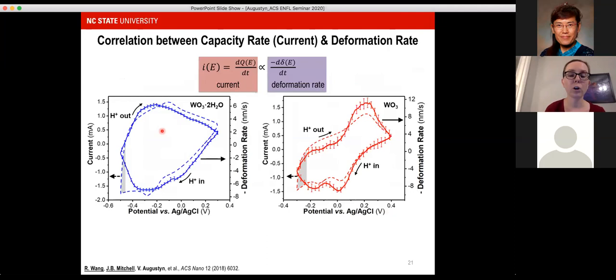The correlation is so close actually that we started to call this result the mechanical CV. The dashed lines here are cyclic voltammograms, so that's measured through the entire electrode in the in situ cell. That's on this axis. These solid lines with the error bars, that's the deformation of the AFM tip over multiple cycles, the deformation rate. And you can see that it almost perfectly matches, qualitatively matches our electrochemical current for both